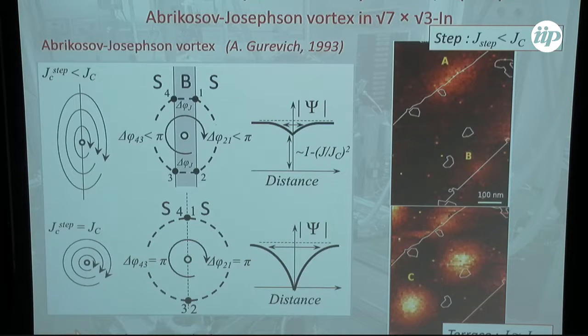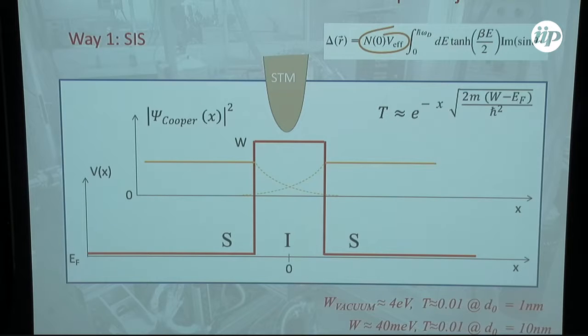So it seems a little bit disappointing because you can understand immediately that if you decrease the Josephson energy, allowing more and more of the vortex perturbation to sit inside, you simply do not see anything by STM. While what we wanted to see is the Josephson vortex core, which supposedly could not exist. So what are the options? A standard Josephson junction, of course you need a Josephson junction for this. Our intrinsic junctions are not appropriate because atomically the width is just one atom, so we cannot go inside. And typically, if you take a standard SIS junction and you put numbers, in order to have a reasonable transparency, you need a width of about 1 nanometer.